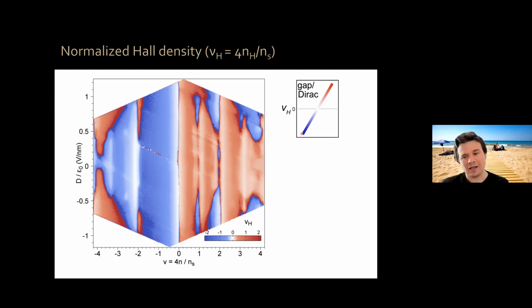So features where your normalized Hall density goes from, let's say, dark blue, which means negative high, to negative low, then to 0, and then to slightly positive, and then to highly positive, those features correspond to a gap or Dirac points. For example, you can see that at charge neutrality, where you have a Dirac point, we go from dark blue to lighter blue, then to white, to light red, and then darker red. That corresponds to your normalized Hall density crossing, as a function of density, a gap or a Dirac point.